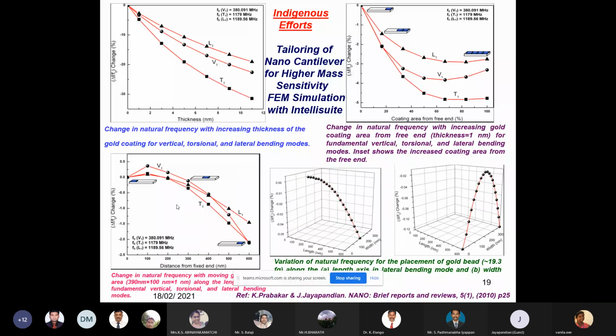Here, on the left and bottom side, instead of this coating, we have a gold coating of 390 nanometer, 100 nanometer, and 1 nanometer dimension. We are moving from fixed end to free end and free end to fixed end, and we are monitoring. The insert shows the coating of the dimension of 390 nanometer, 100 nanometer, 1 nanometer. Then we are observing the resonant frequency shift.